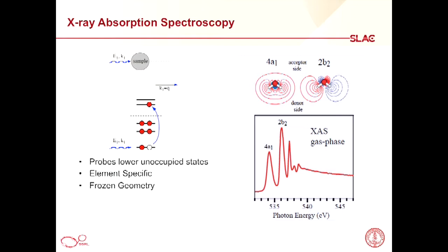One very specific thing, and we're going to mention it a few times, and it was mentioned briefly in the previous talk as well, one of the most important advantages of X-ray spectroscopy compared to other techniques is the element specificity, that somebody, by tuning the incident energy, can probe a very specific atomic species compared to everything else that is available in a sample. And this can be very advantageous when we have very dilute samples. Imagine we have a metallic species and around thousands and thousands of oxygens and nitrogens of organic matter, and then you can still try to specifically excite the specific atom and distinguish the signal from there compared to everything else, something that is not feasible with many techniques that are not element specific.